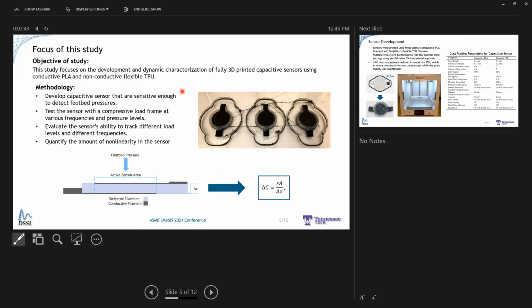So for this work, we focused on developing fully 3D printed capacitive sensors made out of conductive PLA and non-conductive flexible TPU, and then dynamically characterizing those sensors using a compressive load frame at various frequencies and pressure levels. Then we evaluated how well these sensors were able to track the dynamic changes in pressure and quantify the amount of nonlinearity we expected to see in these sensors.